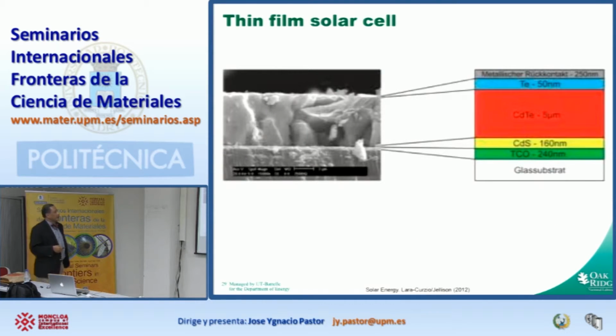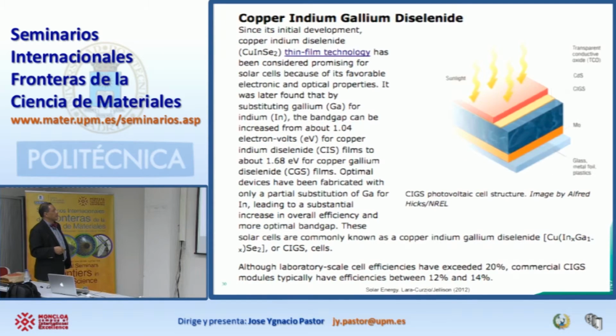If you cut a cell and you look at the cross-section, this is what a cadmium telluride cell looks like. You have the bulk, which is cadmium telluride. Here you have your cadmium sulfide, a very thin layer. You have a glass substrate in this case. Then you have your metallic layer on the back to close your circuit. We talk about the CIGS, these copper, indium, gallium diselenide, very thin layer materials. In this case, they use molybdenum in the back. This very thin layer of molybdenum is deposited onto a glass substrate.